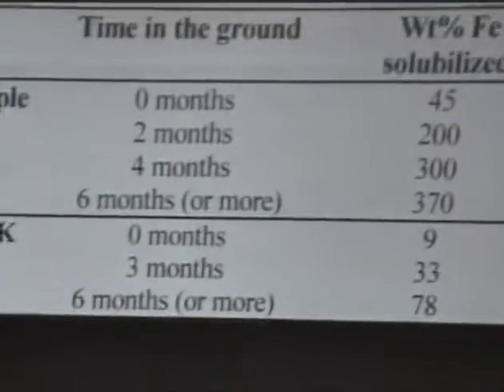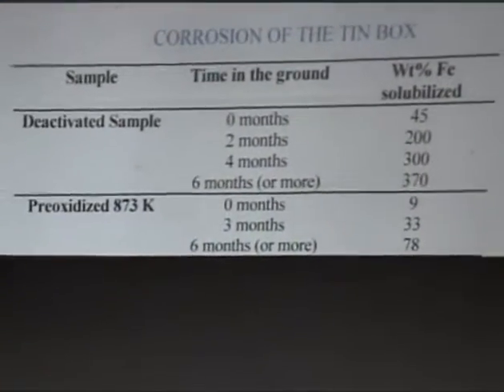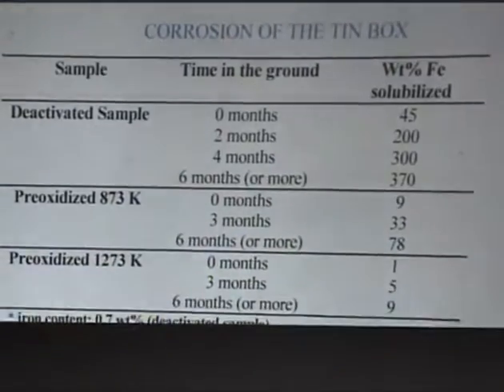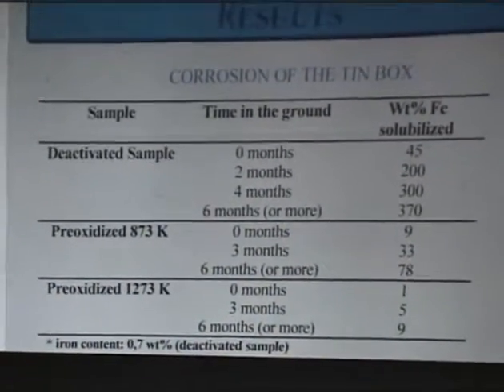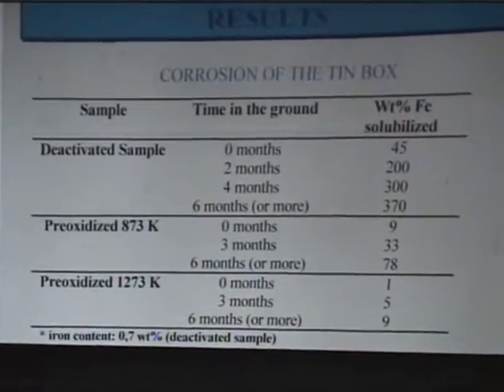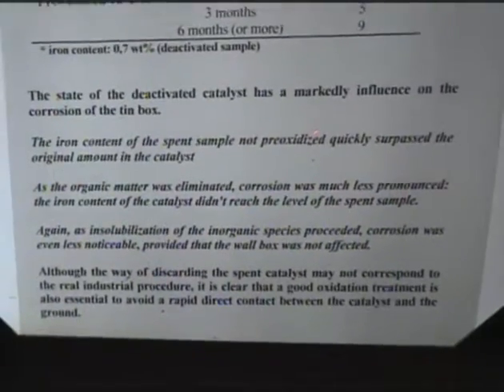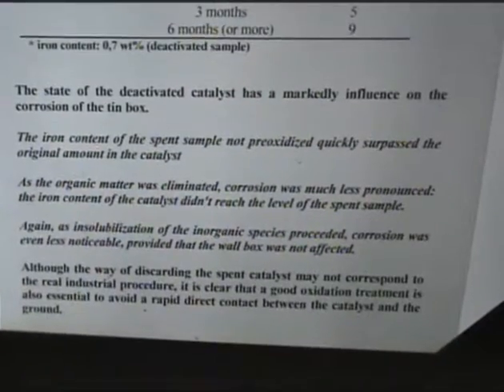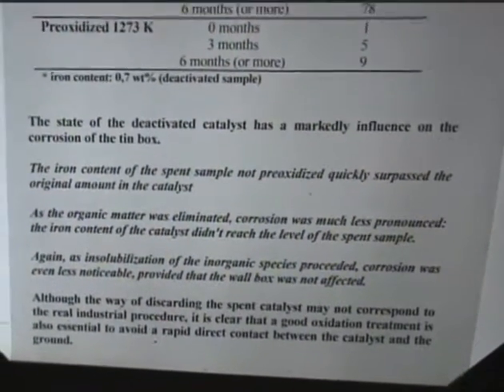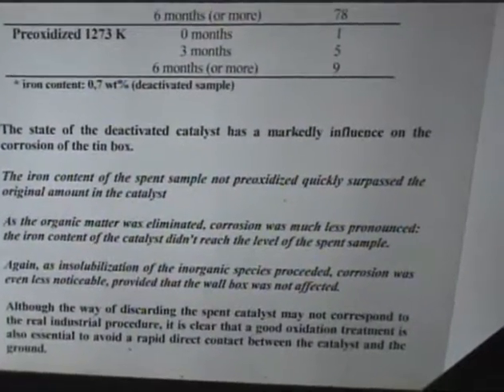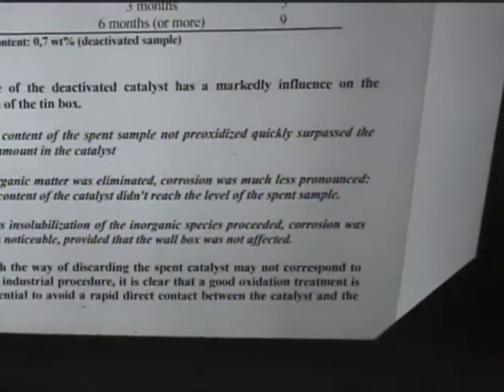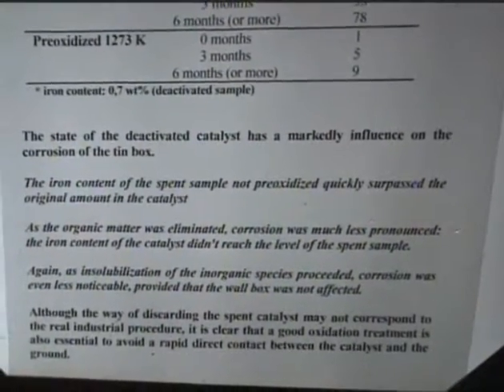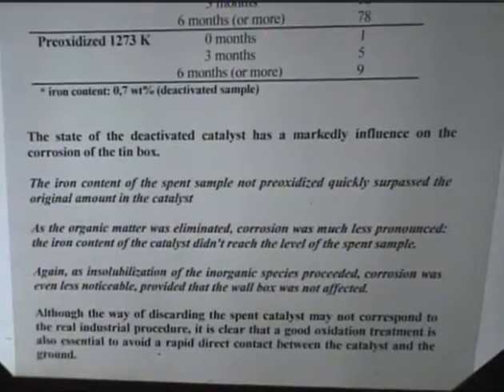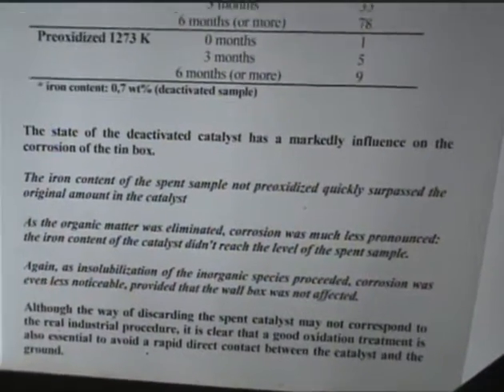After preoxidation at a lower temperature range, the amount of soluble iron was much less important. And finally, when the same catalyst was oxidized at high temperature, the solubilization was even less important. It's easy to observe that the state of the deactivated catalyst has a marked influence on the corrosion of the tin box, the iron content in the case of the deactivated sample quickly surpassing the total amount of the catalyst. As organic matter was eliminated in this case, corrosion was much less pronounced. Again, as the elimination of the organic matter proceeds, corrosion was even less noticeable.